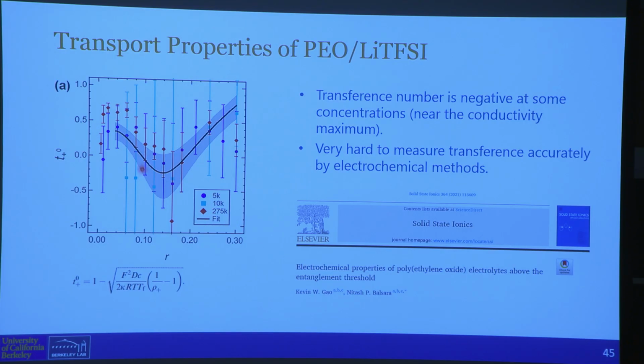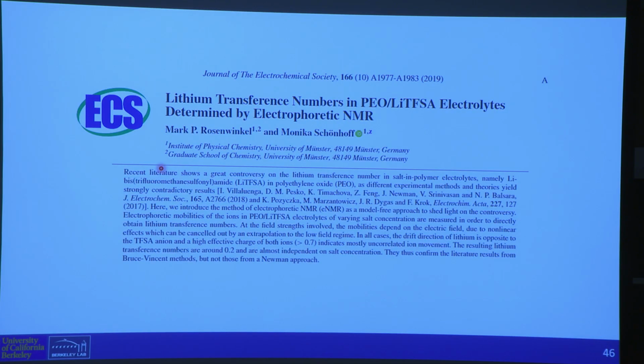And you see the data. It has lots of error bars. You will see much cleaner data in the literature, but with no error bars, because they don't tell you what the uncertainty is. And one thing that struck us was that this transference number, near the peak of the conductivity, is actually negative. This caused a little bit of turmoil.